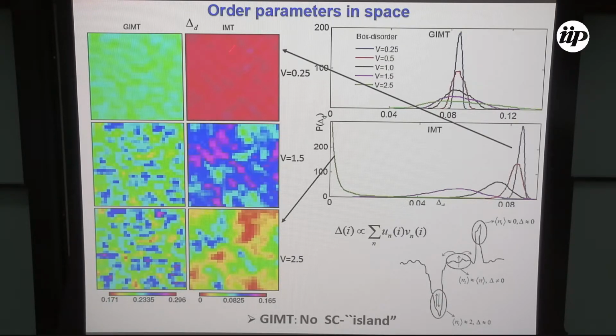So what is this? This is a 30 cross 30 lattice. We plot the superconducting order parameter itself. For low disorder, it should be more or less the same everywhere. If you increase the disorder, you form superconducting puddles if you don't have strong correlation. Why do they form? You can look at this schematic. If you have a high hill, electrons would not be there, so the density would be 0. Because the density is 0, the order parameter would be 0.